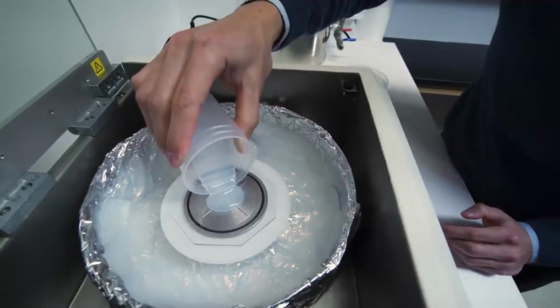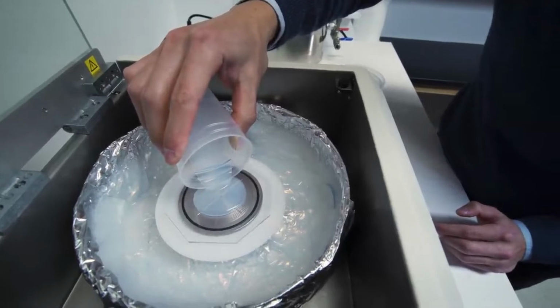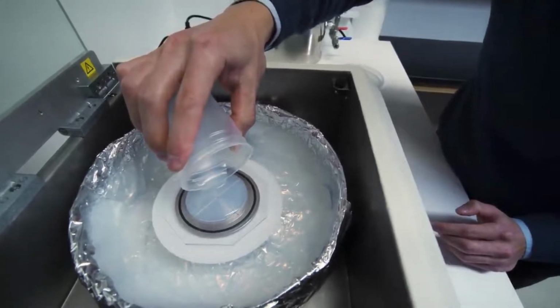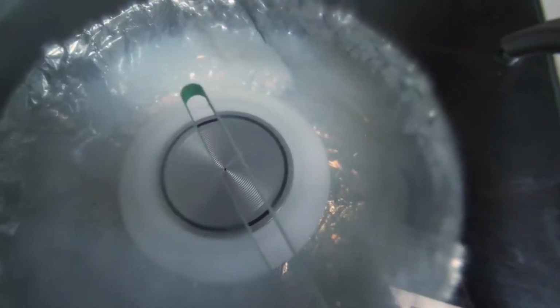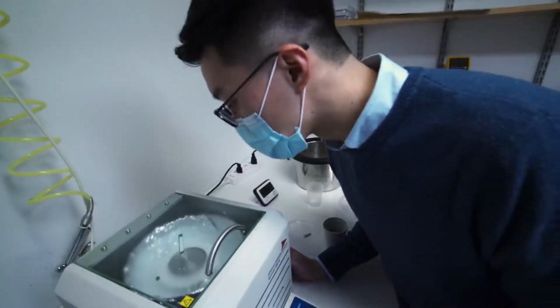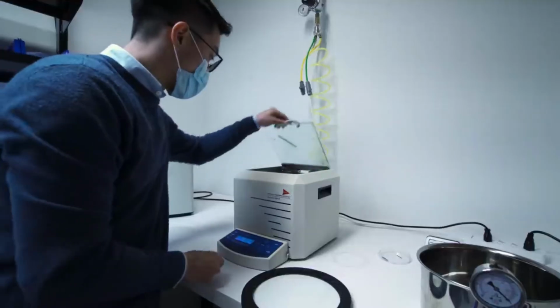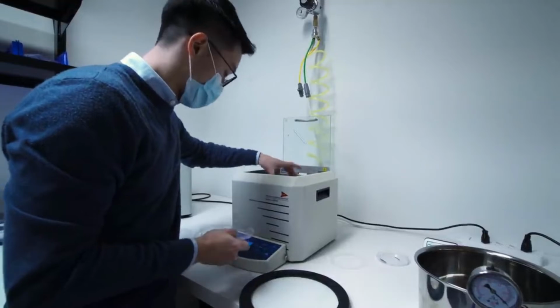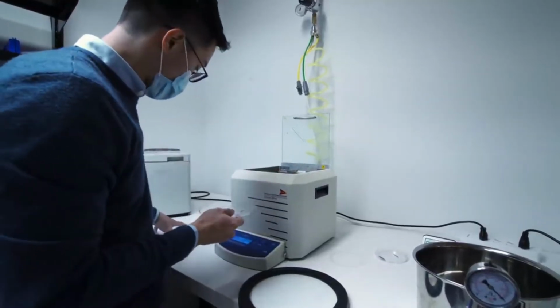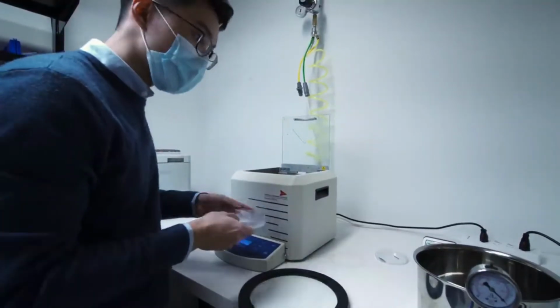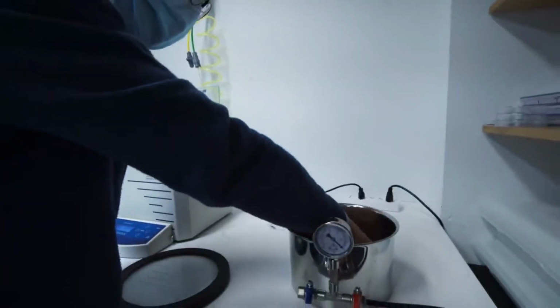They had to overcome a major issue caused by the spin coating process. During spin coating, an elastomer is poured onto a flat surface and rapidly rotated. Tiny air bubbles appeared in the elastomer as the thickness decreased. The solution to this was an additional vacuuming process immediately after the coating, while the elastomer was still wet.